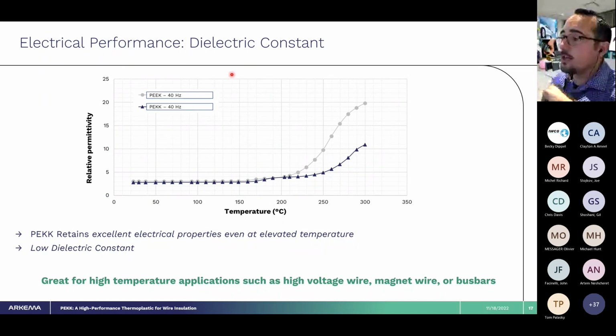So what I've got here is the dielectric constant, and like some of the other data I showed you before, this is going to be both at room temperature all the way up through hot performance. The black or darker blue line is our PEKK material, tested at 40 hertz. We have other test data, 60 hertz, 1000 hertz, which I could show at a later date. But just to show you the PEKK material at 40 hertz as compared to the PEEK material also at 40 hertz, you can see at room temperature and things, we're close.